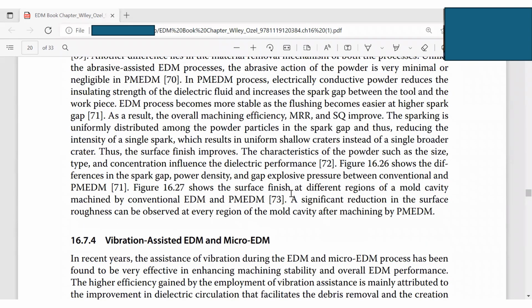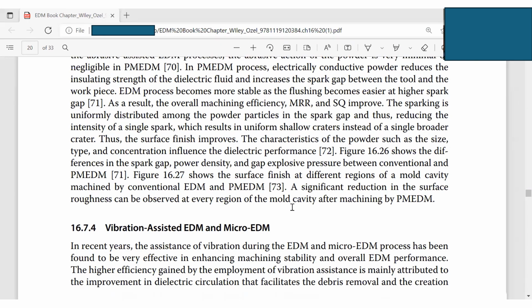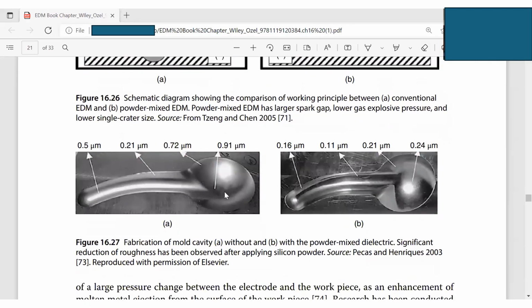Next picture shows the surface finish at different regions of a mold cavity machined by EDM and PMEDM, 16.27. So this picture is the fabrication of a mold cavity. Okay, so this is the mold cavity without the powder. So this is with powder. So as you can see, a significant reduction of roughness has been observed. This is much shinier and smoother after applying silicon powder.